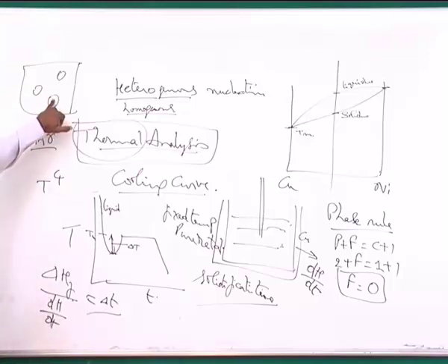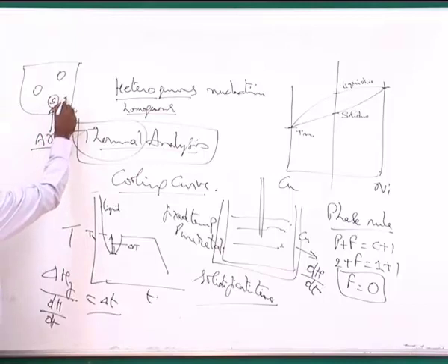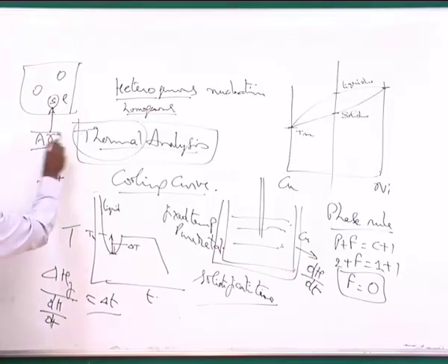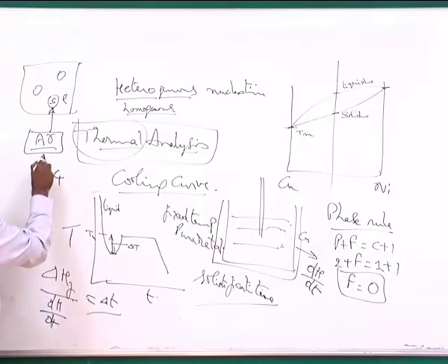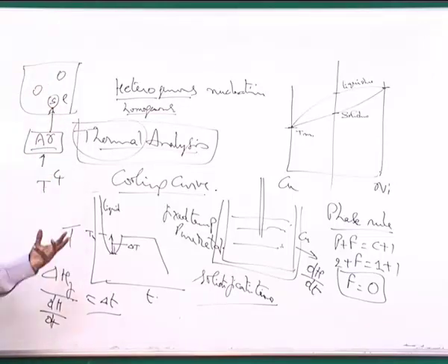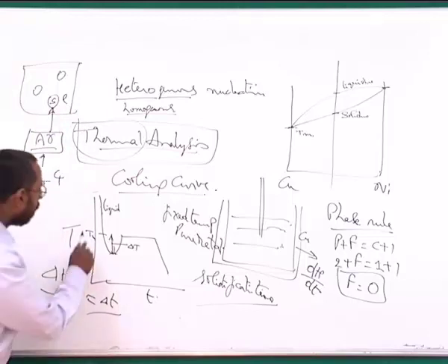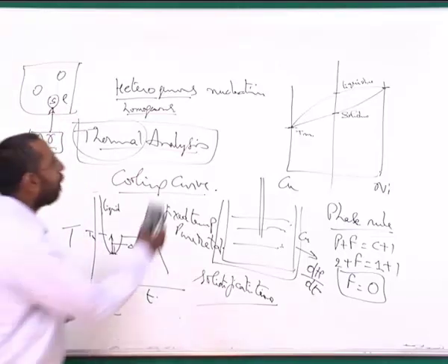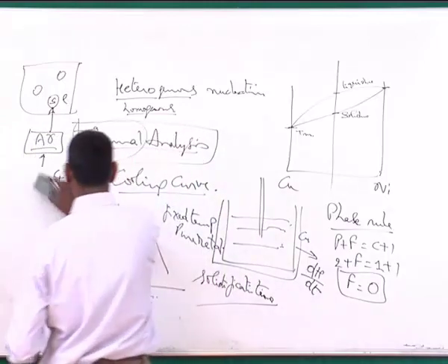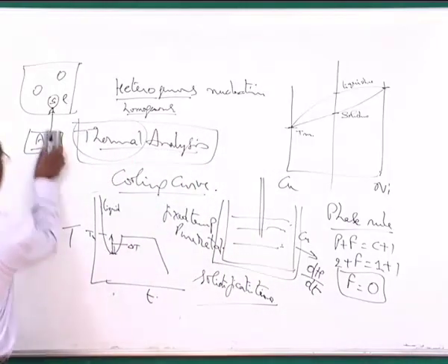Depending on the surface energy per unit area of this solid with respect to this liquid, and whatever the surface area associated with it, this Aγ will represent the total energy that needs to be spent for creating this solid. And this energy has to be spent only from the excess energy that is contained in the liquid.